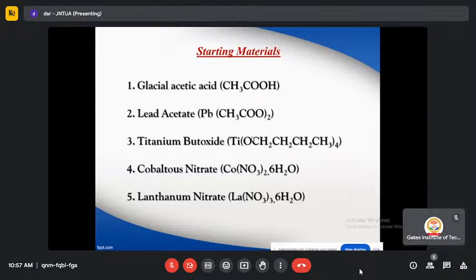Then, the attained powder was sintered at 750 degrees centigrade in a microwave furnace for around 1 hour. Further, the crystalline powder was ground again to get a fine powder. Then the pellets were prepared by maintaining a pressure of around 10 tons in the hydraulic press. In addition, the prepared samples were characterized using several techniques like X-ray diffraction, field emission scanning electron microscope, etc. So once the materials are prepared, they should be characterized for studying many things like the size of the nanoparticles, what strain they can withstand, and so on and so forth.